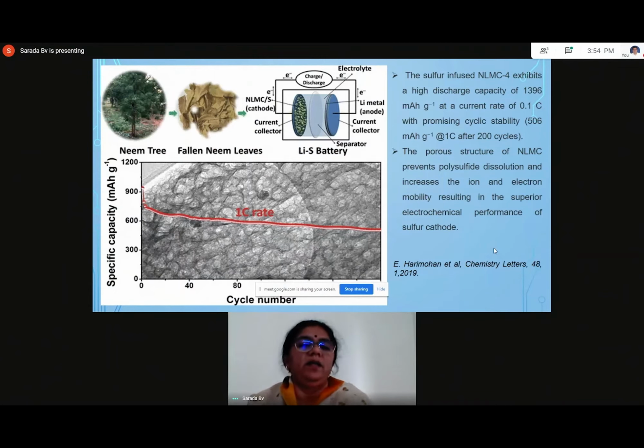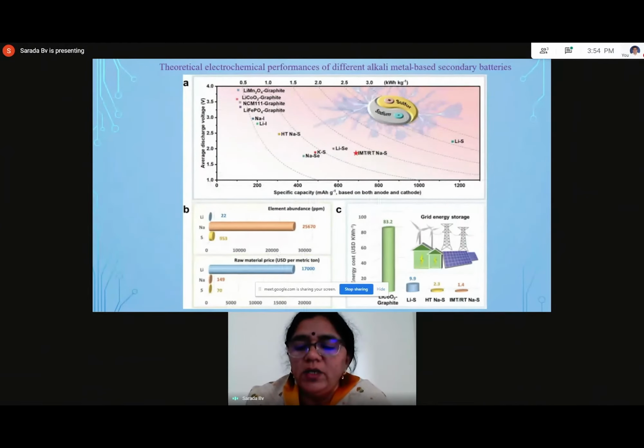And we have demonstrated the working of coin cell by lighting LEDs and also running a fan by using this cell. Another bio-waste material used is the neem leaves, which have fallen from the tree. These are collected and made into porous carbon material, and made into a lithium sulfur battery, which has again given 506 milliamp hour per gram after 200 cycles, and has very good stability. So it is proven that when we can bring the optimum loading of sulfur into the pores, the carbon with pore size in the meso or microporous range can give the best results.